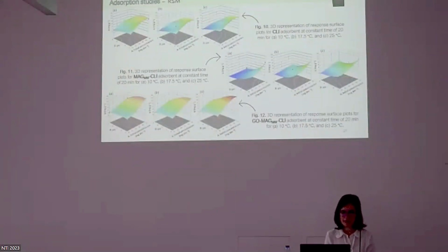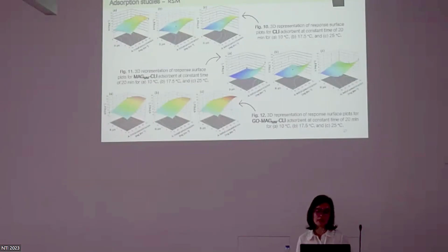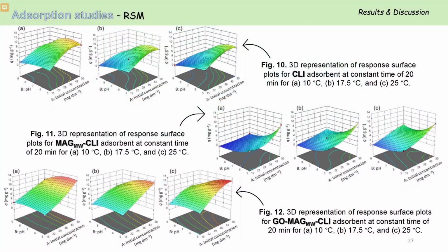The most significant variables of ciprofloxacin adsorption are first the initial concentration of ciprofloxacin, then the pH, then the type of adsorbent, and these are linear parameters, and then the combination of initial pH, temperature, and the adsorbent type, which is also shown here. What we can see from this plot is that the adsorption capacity strongly increased with the initial ciprofloxacin concentration, and that it also decreased with changing of pH from 5 to 9. So in this case, for the studied range, the optimal pH was found to be around 5.